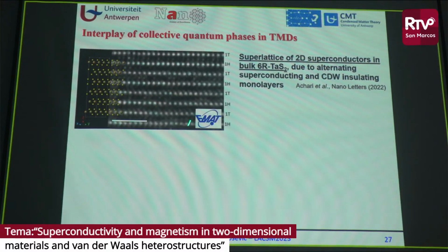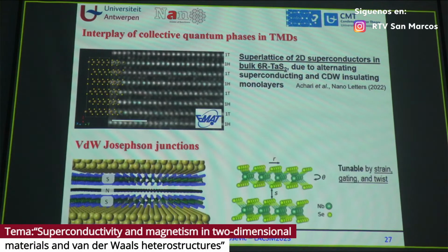So we went on to make a heterostructure that contains monolayers of superconducting tantalum disulfide and monolayers of non-superconducting. So this is the so-called 6R phase of tantalum disulfide. We have one H monolayer, which is the superconducting layer that I just showed you a moment ago, and one T monolayer, where you can see here the difference in where the sulfur is sitting with respect to the tantalum, between one H and one T. Okay. One T is an insulator and presents a charge density wave. One H is a superconductor. So what you get here is a stack of superconducting layers separated by an insulator. And these are basically ideal van der Waals Josephson junctions.